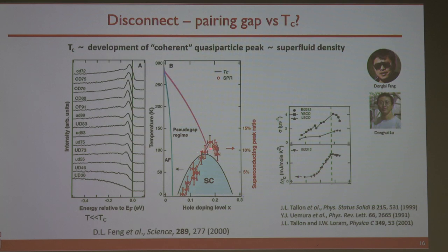But more importantly, what we are measuring is the so-called single particle Green's function. You take an electron out and measure the spectral function. We should not have the result sensitive to superfluid density, which is a 2-particle correlation function. But nevertheless, empirically, this result correlates with superfluid density extremely well. Okay, so that is another term. To tell you again, this TC is not connected with the pairing.